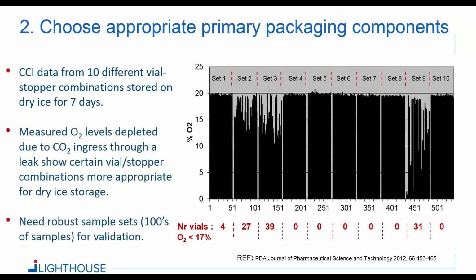And from this data, you can see that a number of vials have depleted oxygen levels, and that certain vial stopper combinations actually have quite high failure rates. So you see set 3 there, 39 of the 50 vials show depleted oxygen levels. Set 9, 31. These are all vial stopper combinations that worked at room temperature but do not work at deep cold storage. So you need to have this robust data. You also need to have robust sample sets, so hundreds of samples. It's hard to make conclusions if you're only looking at sample sets of 5 or 10. So again, here an example of CCI data that allows you to choose appropriate primary packaging components for deep cold storage.